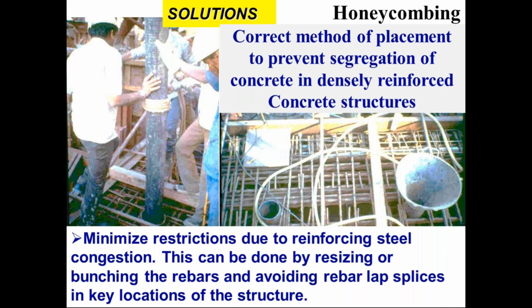No splatter on the reinforcement bars with mortar is seen. It's a clean operation. And on the right hand side, you can see the bunched bars and the properly spaced bars. Even in the cover region, we made sure that the 60 millimeter needle goes right down when it is vibrated. Between the reinforcement and the formwork, there is enough gap to vibrate the concrete.